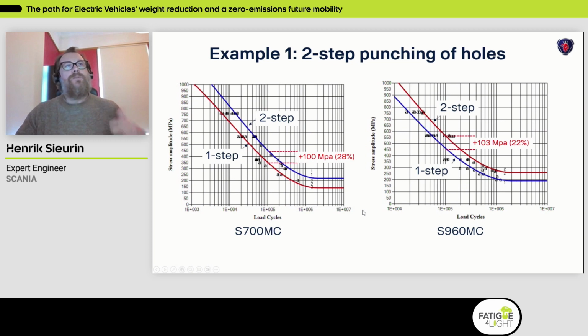In this project, we obviously did fatigue testing of punched holes, comparing the traditional one-step punching and the two-step punching. And these are the results for the 700 MC material. I would mention also that for a truck chassis, it's generally around 100,000 cycles that we dimension for. So at this value, we increase the fatigue strength by about 100 megapascals. That's 28%. So that is, I would say, a huge increase by a relatively simple method. And for the 960 material, we see a similar increase.